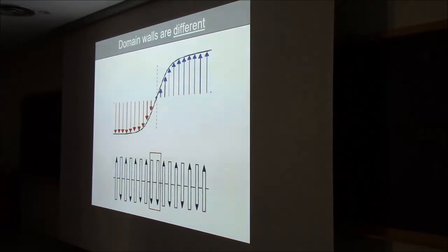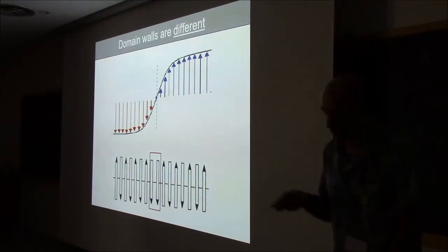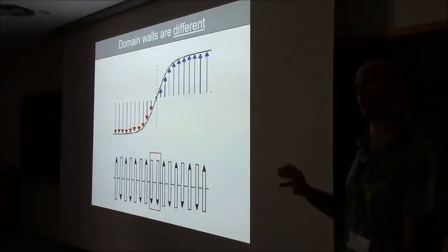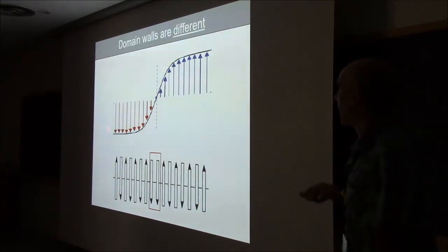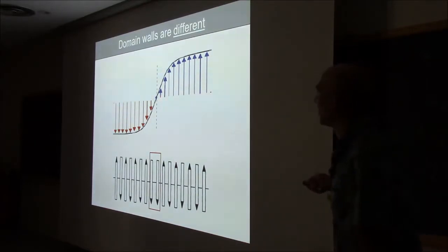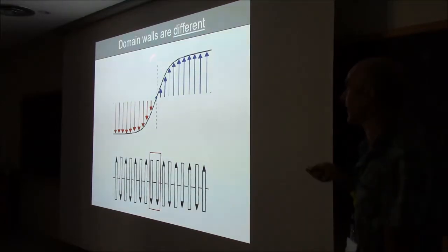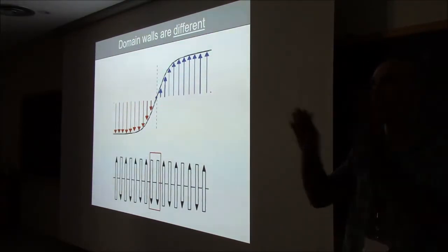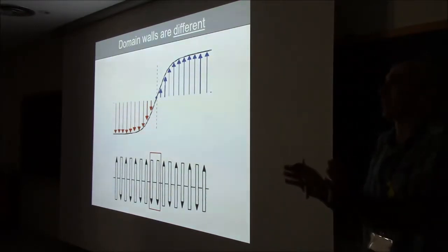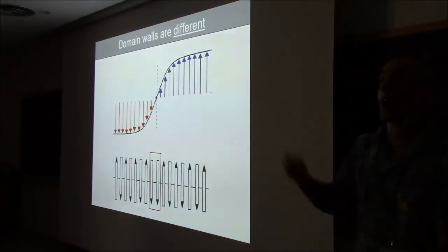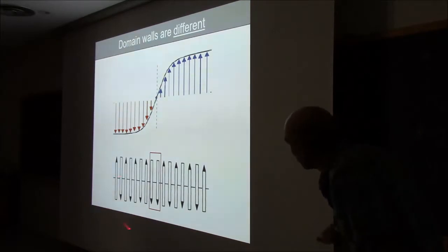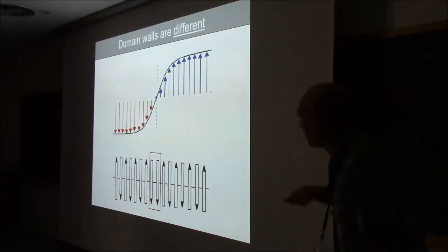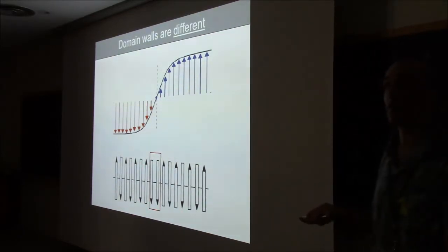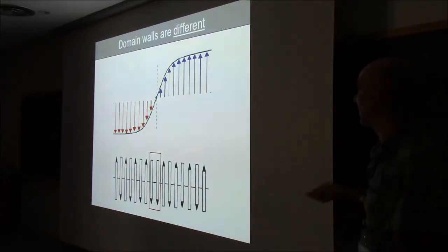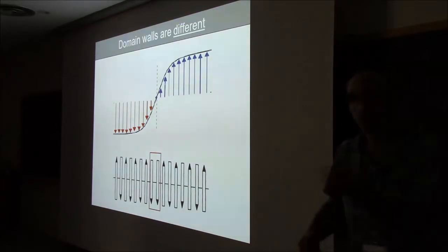I'm saying this because this is a fairly hot topic in ferroelectrics at the moment. And it's a hot topic because domain walls have completely different properties from those of the domains they separate. Trivially, if you have a domain wall separating down polarization from up polarization, the polarization of the domain wall has to be zero, at least along the polar axis. So you have a non-polar entity embedded within a polar matrix. So you can trivially see that the domain wall has different properties. That's true for ferroelectrics. For antiferroelectrics, you have the opposite. If you have your up, down state, and then the next domain being down, up, this antiphase boundary is polar. You have two dipoles that are not compensated, even though the material itself is non-polar. These are trivial examples.